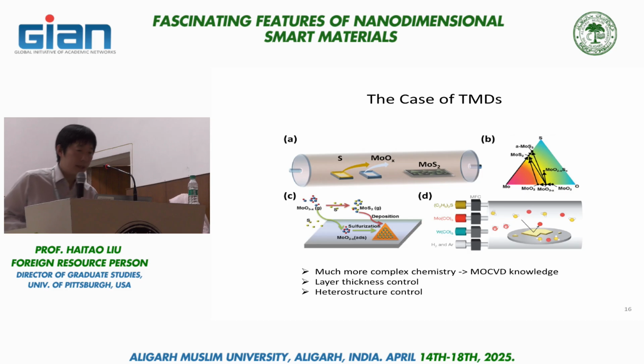In this case, the basic growth principle is still the same. You have a high temperature environment, you have some kind of precursor, and they combine together, and you limit their growth into a single layer, and then, wow, you got single layer TMD. But the chemistry is much more complicated because a lot of the precursors are not as simple as methane. Now you have two. And in particular, one of the components is a metal, and that severely limits the kind of choice you have because a lot of metal precursors are not volatile, even at pretty high temperature. By the nature of the name, chemical vapor deposition, you have to have some kind of mechanism to transport the precursor in the vapor phase.